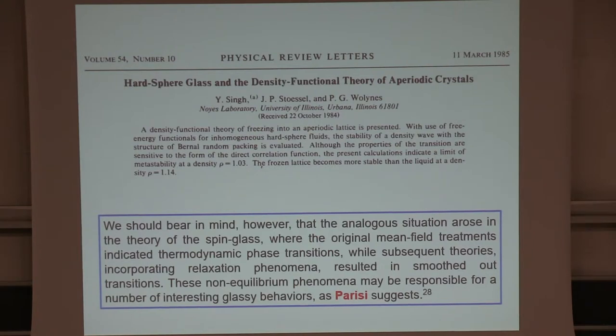And on the other hand, at that point, the free energy of this state was higher than the free energy of a liquid, and you had to go to a still higher density, near to the density of close packing of Bernal, to get this to be more stable than the real thing. And of course, this was so much like freezing that I knew it was wrong. And so that's why we said something in the end,